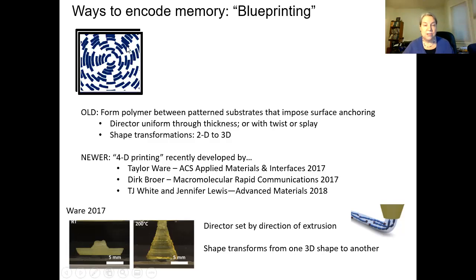And so in this case, once you've patterned the front and back substrates, then you fill it with a liquid which includes liquid crystal monomers, the monomers that are going to make the polymer, and the cross-linking agent. You put that stuff inside the patterned substrates and let the liquid crystal relax itself to align with the pattern on the surface. Then shine UV light through the glass to polymerize it.